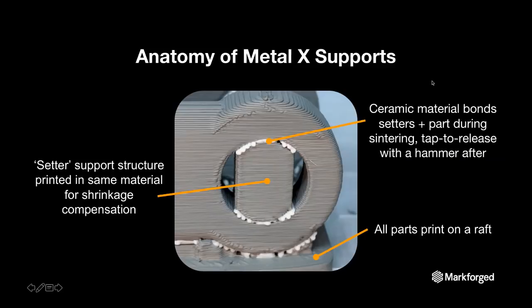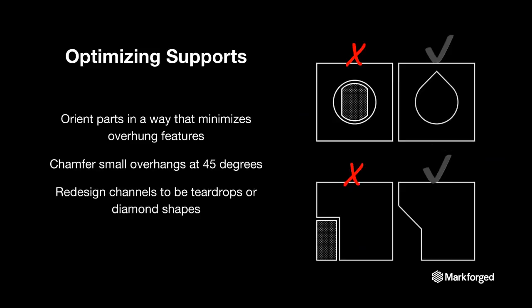But if you're thinking about optimizing them, support material is material that's going to take up more time in the printing process. So if you're trying to print your parts faster, it generally helps to minimize your supports. To optimize them, there's a couple things you can do to eliminate supports in areas where you don't actually need them. For horizontal holes or horizontal bores, and really it's not even so much holes, it's any geometry that's a horizontal path, you can take a circular cross section and add something like a teardrop or change it to a diamond shaped profile to entirely eliminate support generation in those channels. As long as those overhangs are at 45 degrees or less from the vertical, it won't generate any support material in that channel.